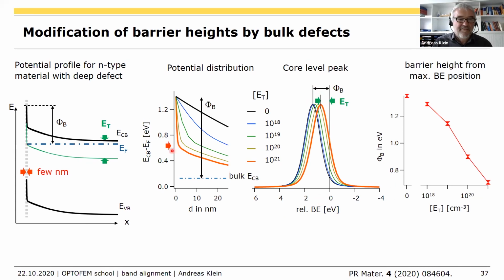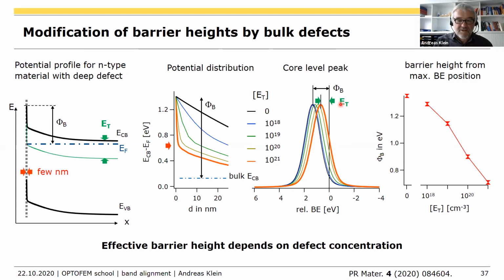This is not only an artifact of the XPS, this is in principle the same for the electrical properties. Because if you have such a narrow space charge region, you have a very huge electric field. It's not only that you get tunneling here, also the image force lowering is substantial. So we did a calculation for zinc oxide, and actually the effective barrier we measure by XPS and the barrier you get by the image force lowering is pretty much the same. So you have to be careful about such defects.